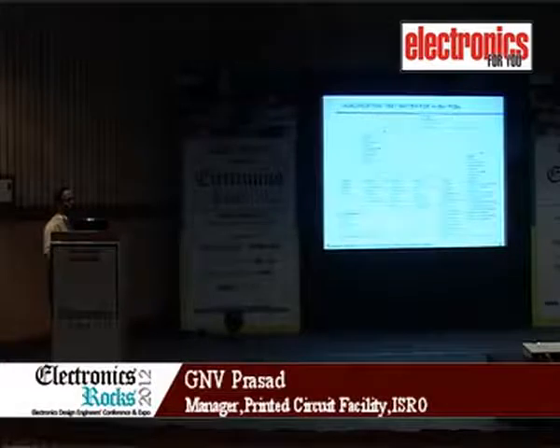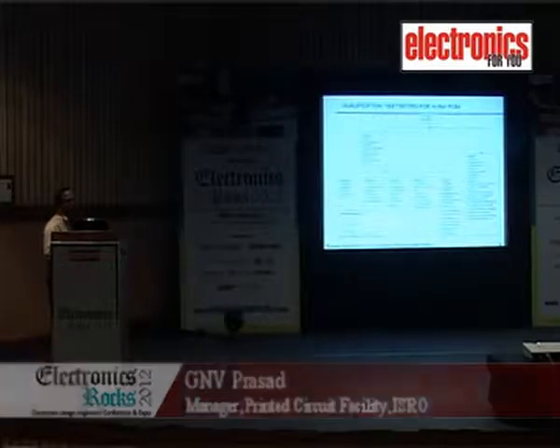The PCBs intended to be used for space application have to be dipped in solder at 288 degrees centigrade 6 times, and we see whether the plated through holes, the pads and other things are still intact. This will be verified by doing the bow and twist test, peel strength test, and microsection of PTHs.